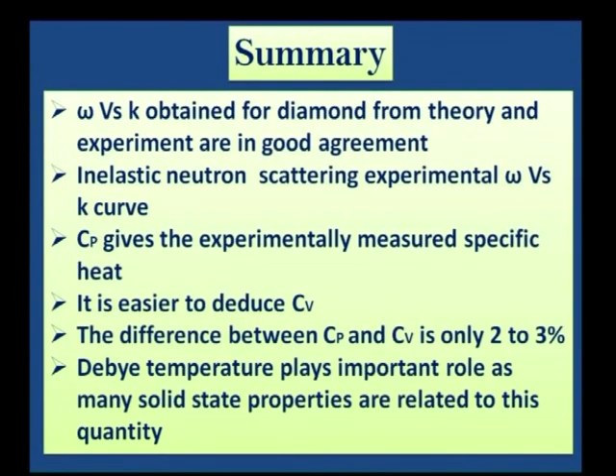Let me now go to the summary part of my last lecture on this particular topic. The omega versus k obtained for diamond from theory and experiment, the agreement is very good. Inelastic neutron scattering experiments are the direct experiments which give the omega versus k curves. Cp gives the experimentally measured heat capacity, whereas the theoreticians obtain Cv because of the reasons I told you earlier. The difference between Cp and Cv is only 2 to 3%. Debye temperature plays a significant role, as many solid state properties which I mentioned earlier are related to this parameter.